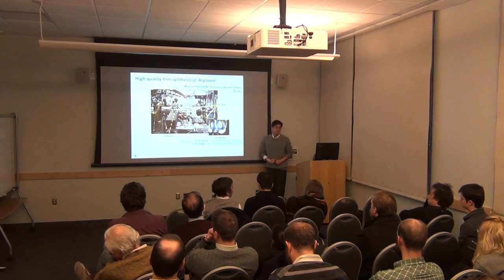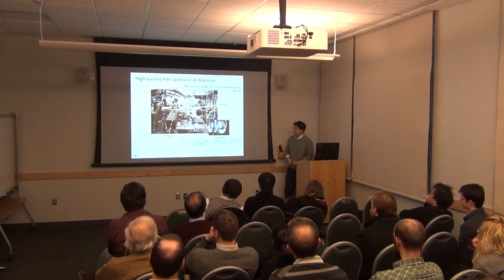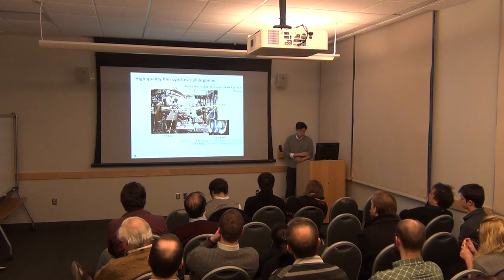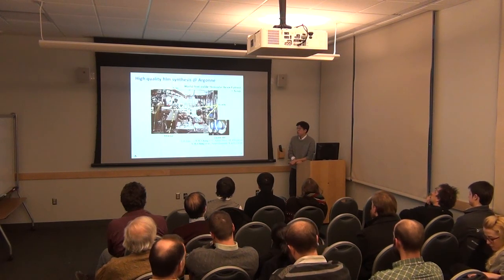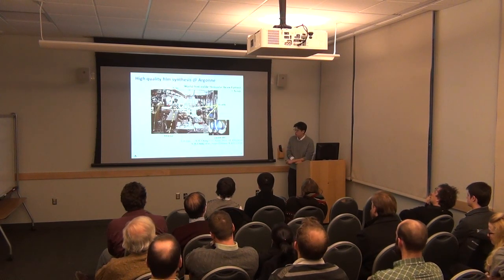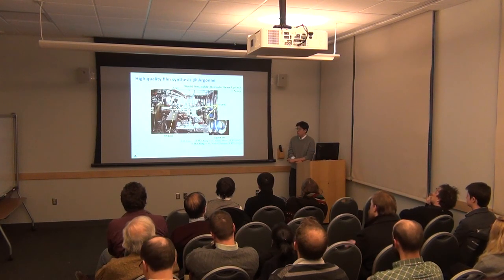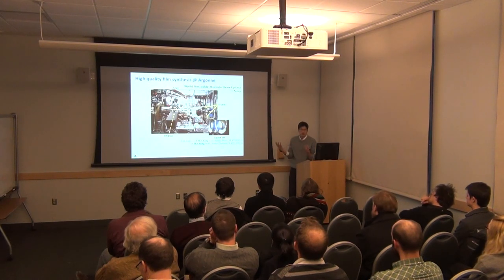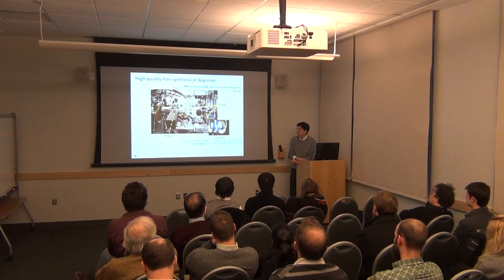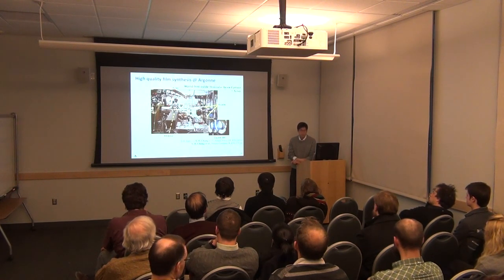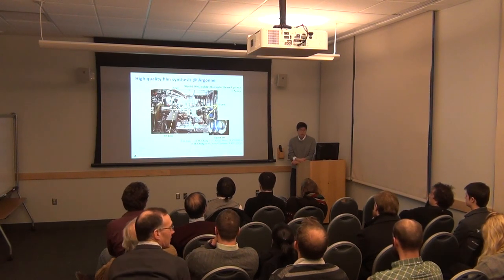So is it better to do it in situ than ex situ? Right, yeah. The power of the in situ X-ray technique is we can monitor right away. If the material is easily degraded in air, then you cannot measure exactly the same structure as at the growth condition. So we need that in situ power. So this is real time. Let's say layers form in real time, and we have snapshots at every moment.